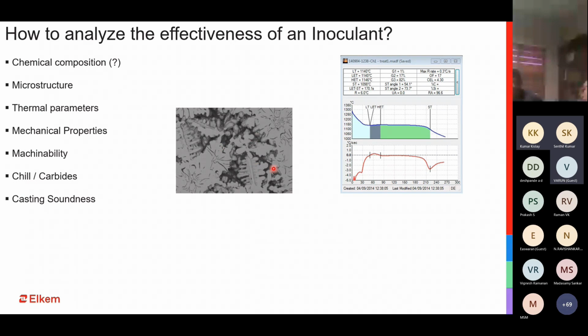So what is happening here? It's a very interesting, typical photograph of a gray iron casting which has these dendrites. These dendrites are the austenite which is precipitating, and this is directional solidification which is happening because you do not have enough nucleating sites. When you do not have enough nucleating sites, the casting would still solidify, but it would solidify in a direction. This is called directional solidification, and this particular branch structure is actually the dendrite. So this dendrite is formed, and this dendrite will make sure that you get more of type D and E graphite precipitating on both sides of it.